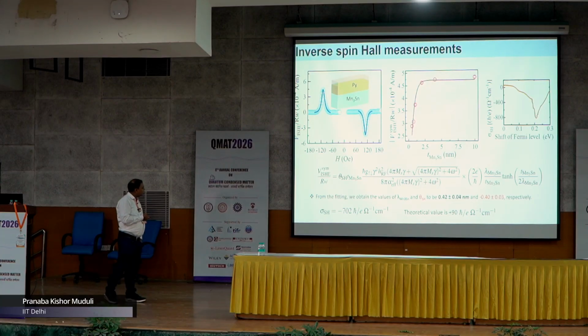Now the interesting point is that this value that we found is quite large actually. If you compare to the theory that I previously discussed, the theoretical value is actually positive. In the experiment we found it to be negative and also quite large. And we think that this is related to the fact that in a real sample, because we have a little bit of excess manganese, the Fermi level is slightly changing, and maybe that is the reason why. If you try to calculate the spin Hall conductivity as a function of shift in the Fermi level, you can see that it is positive in the beginning, but it can immediately change the sign and become very large, and that may be the reason why we are seeing this large and negative value of spin Hall conductivity.